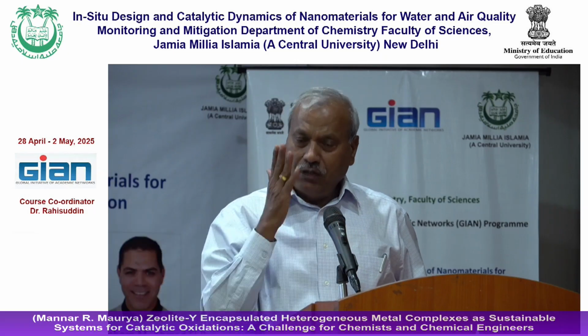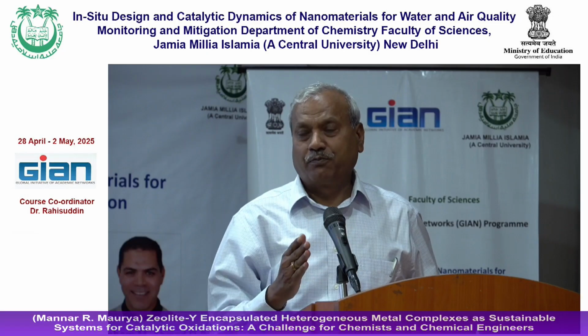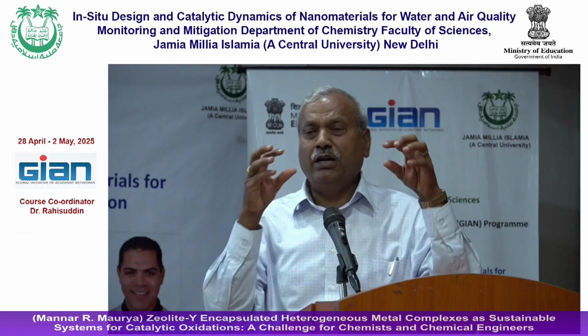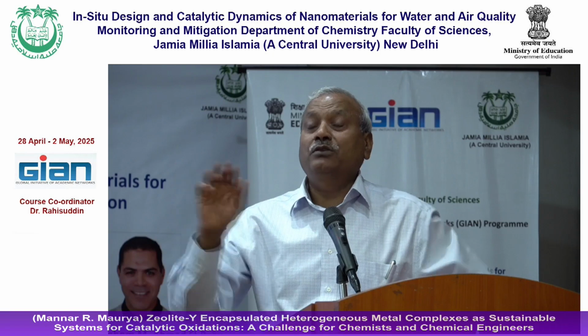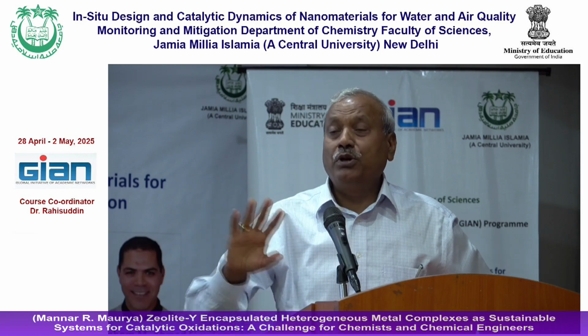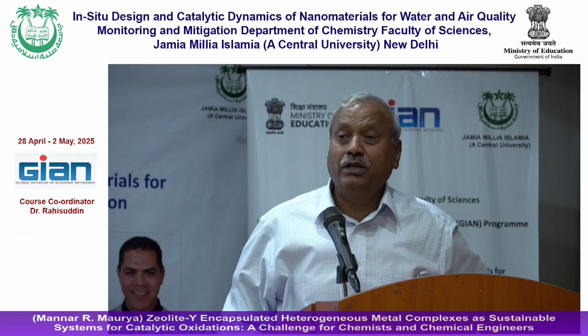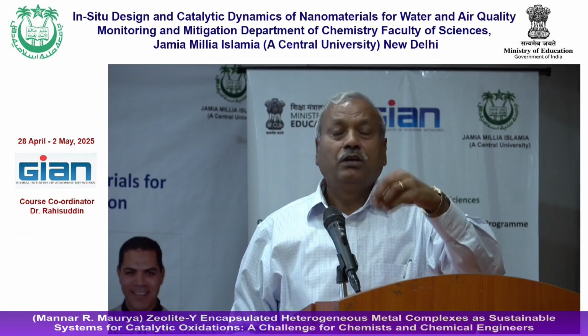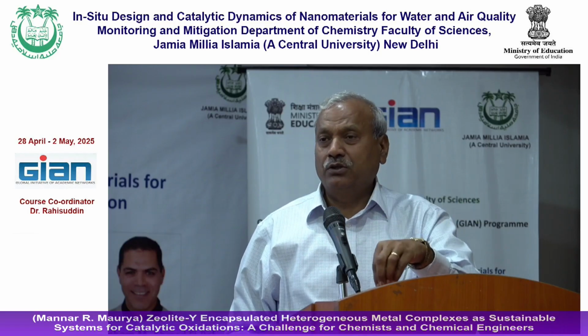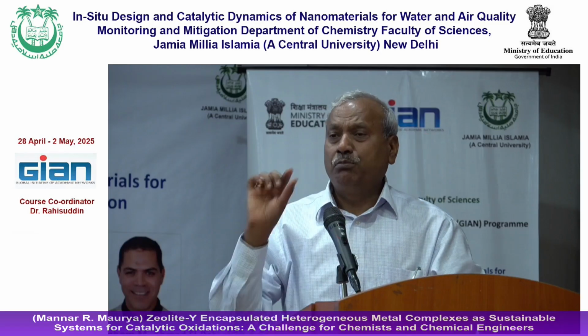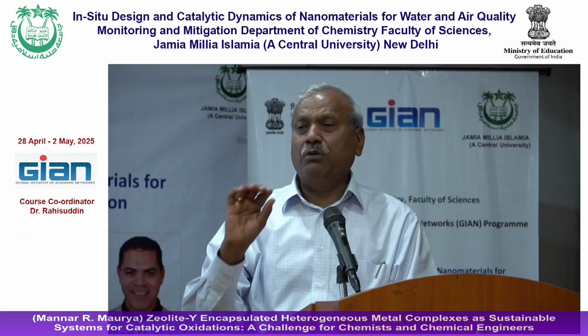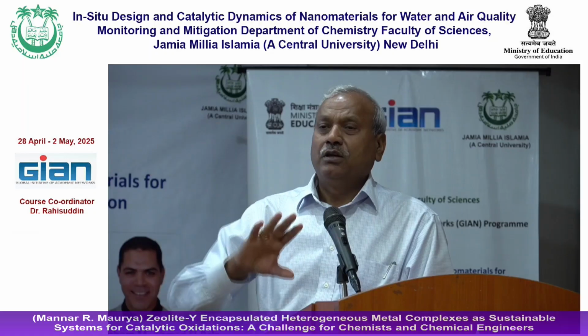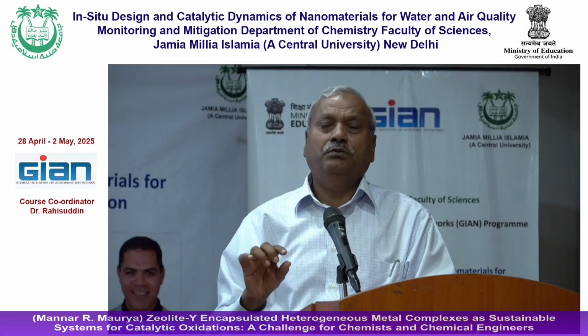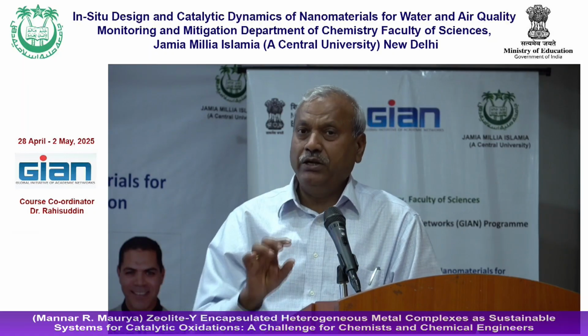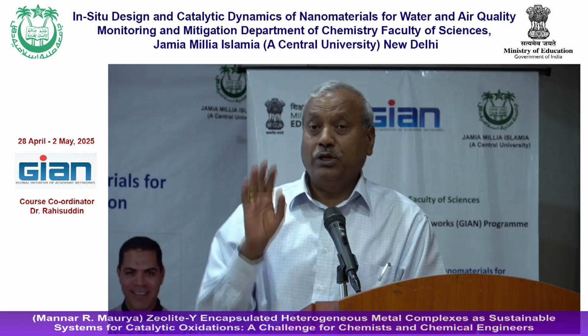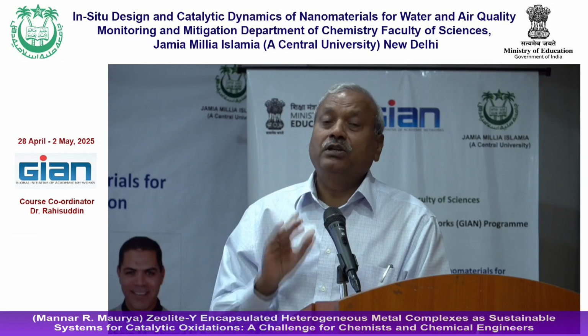Now if leaching had occurred, then on adding substrate and oxidant, more reaction should occur. But there is no further reaction after adding extra substrate and oxidant. The reaction is not moving. The percentage of conversion remains the same, meaning there is no leaching of metal complex during the catalytic activity. So that is a good part, meaning the catalyst is recyclable.